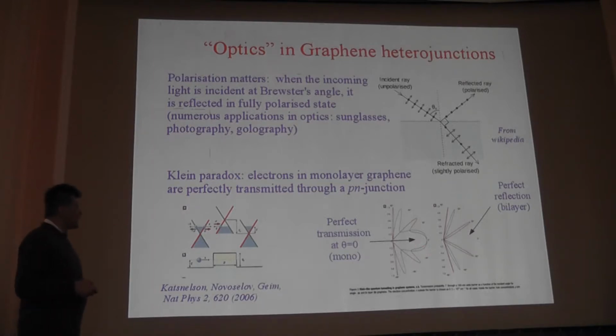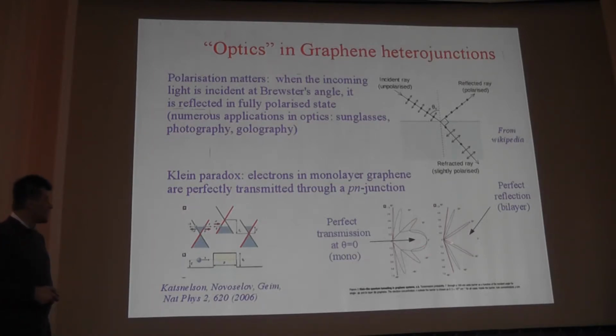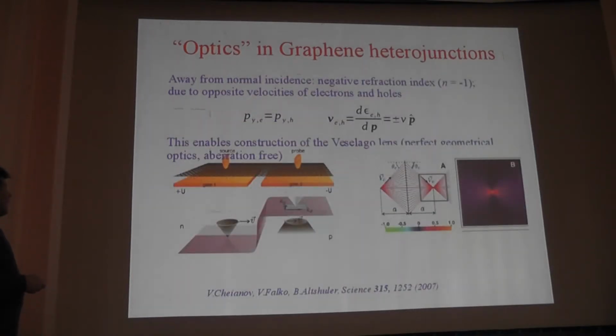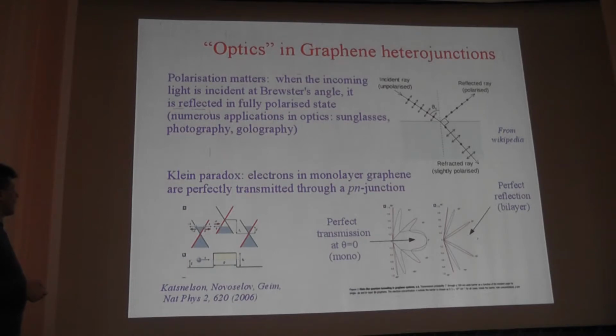For bilayer graphene, the chirality pattern is different, and the result is that you have a perfect reflection at normal incidence. Nothing is transmitted. Normally, in quantum mechanics, you learn that for nearly any reasonable barrier, transmission is different from one, and reflection is different from one. Sometimes the transmission is very small, sometimes reflection is very small, but they are never equal to 1 or 0 exactly. In this case, it does happen because of the chirality of charge carriers. So that happens at normal incidence.